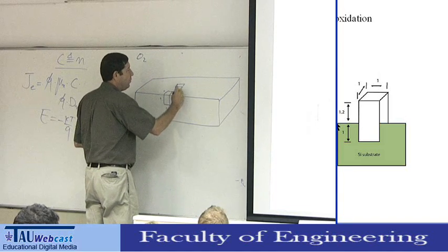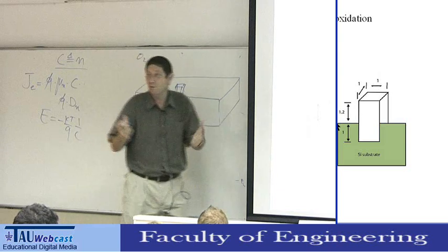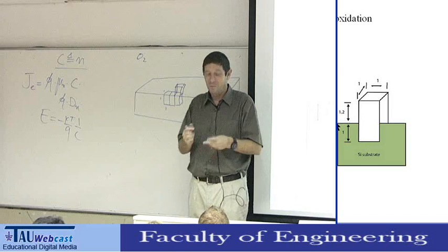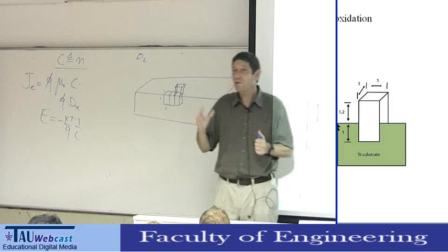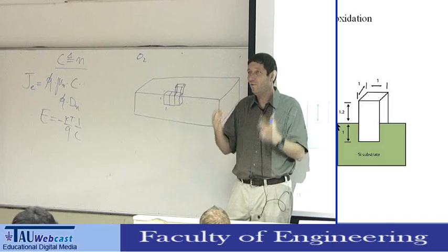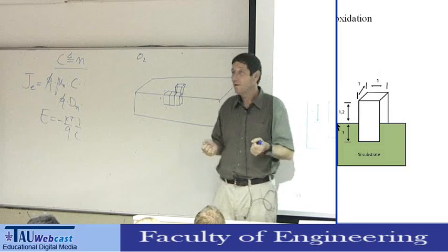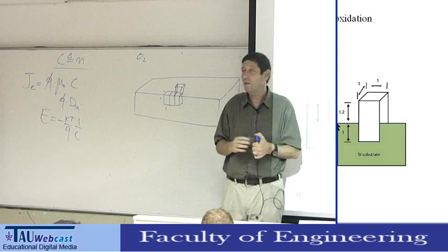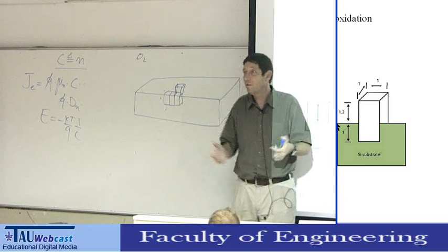Because the volume should grow, because we generated oxide. Now, luckily, oxide is elastic enough and can flow, so it doesn't break. But if you grow, for example, a much tougher material, it could break. It could get cracks.